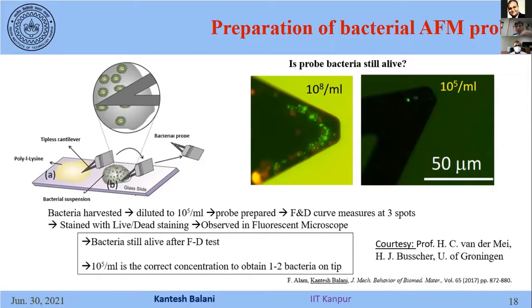So now I'll lower the concentration. Now here I'm seeing that I only have 1 bacteria. This is a fluorescent image. We have tested before and after the testing, and we still see there is only a single bacteria on the cantilever. 1 or 2 bacteria is acceptable, but we would like to get signal only from 1 bacteria.